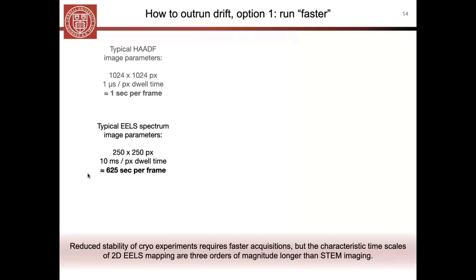And so what that means is that if you use those analytical drift speeds that I've already shown you from these side entry cryo holders, over the course of time that it takes you to do this kind of EELS map, you're going to drift by more than 100 unit cells, which in almost all cases is going to drift right out of your frame, your field of view.